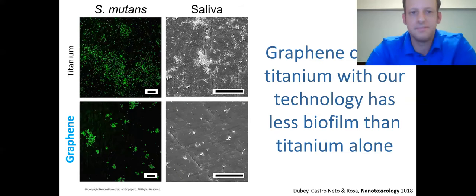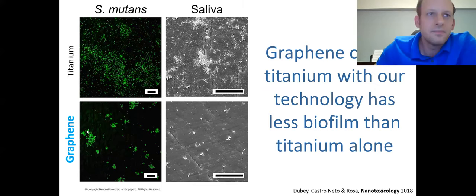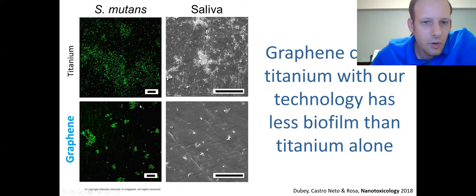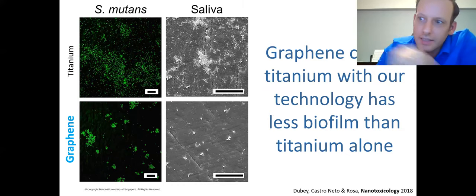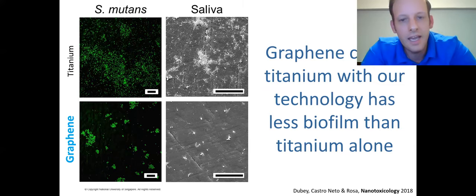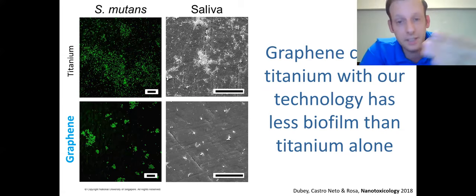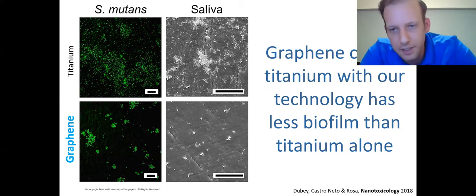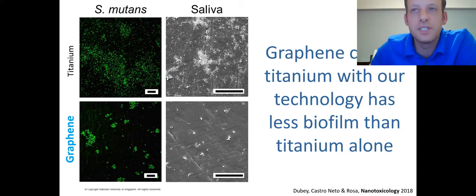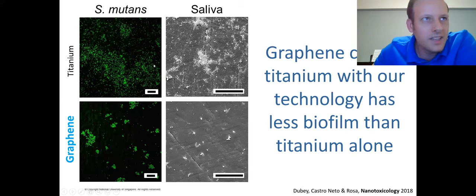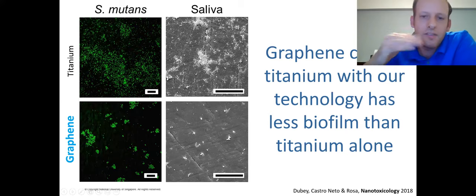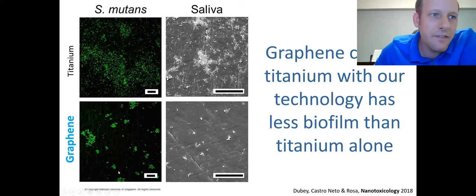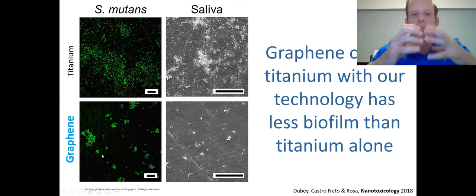Our first work with graphene was published some time ago, and it was a very practical work. At that time we got some titanium coins, and we coated them with graphene. And we started culturing some simple bacteria, what we call gram-positive bacteria. And what we observed was that on titanium, as expected, there was lots of biofilm formation, but on the graphene-coated specimens, that was just not happening. We have very few biofilm clusters here and there, and they fail to merge.